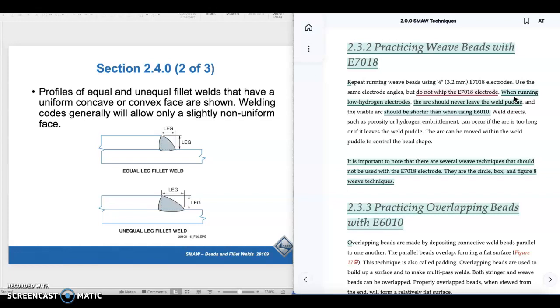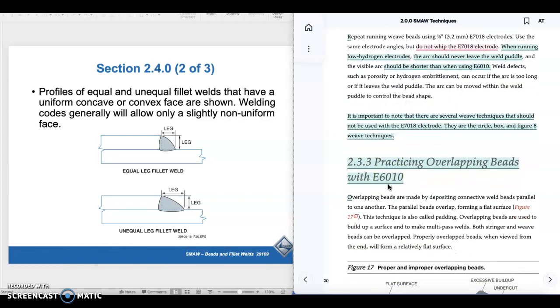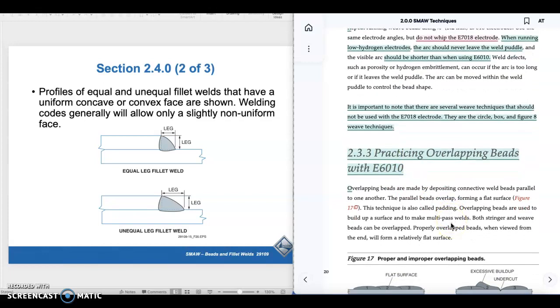In addition to not whipping it, anything excessive with the 7018 is going to give you a less than desirable result. Weld defects such as porosity and hydrogen embrittlement can occur if the arc is too long, or if your rod leaves the weld puddle. The arc can be moved within the weld puddle to control bead shape. It's important to note that there are several weave techniques that should not be used with the E7018 electrode. They are circle, box, and figure 8 weaves. And that's probably because you end up leaving the puddle.